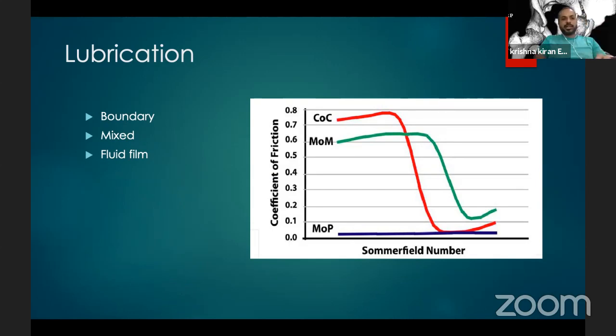So you have 3 types of lubrication. In an ideal scenario, you'll have what is called fluid film lubrication, where throughout the walking and standing phases, you will have a full thickness fluid film separating the 2 opposing surfaces, the femoral head from the acetabular cartilage. That is the normal situation. The in vivo scenario where we have a hip replacement in place will have varying phenomena, and that is measured by the Stribeck chart, and by a number called the Sommerfeld number. As you approach 1, you will have fluid film lubrication, which happens with hard on hard bearings, so ceramic on ceramic, or metal on metal with large diameter heads. A fluid film is possible, so the wear rates in these bearings will be lower.